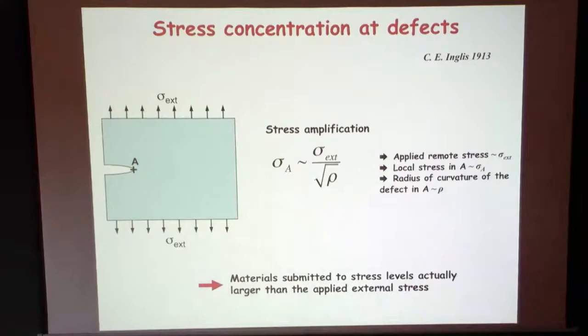My students always ask me this question when they start in the business, so I even have an answer. Okay, this is an asymptotic expansion, so you're looking at the nastiest component of the stress field. This is just the first term in this expansion, but it's the only singular term. As Laurent will show us, it turns out to be universal. All the non-universal parts of the stress field, you just add to it. But as you get near the tip, this thing dominates. So you can explain all of fracture mechanics just by the existence of the singularity.